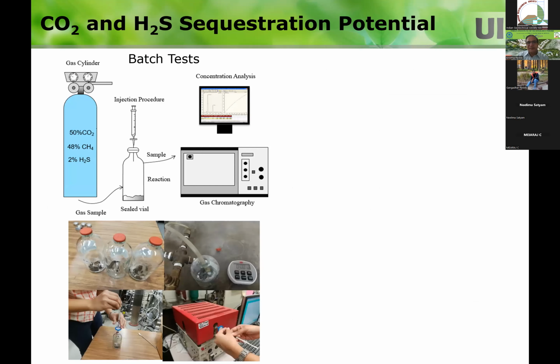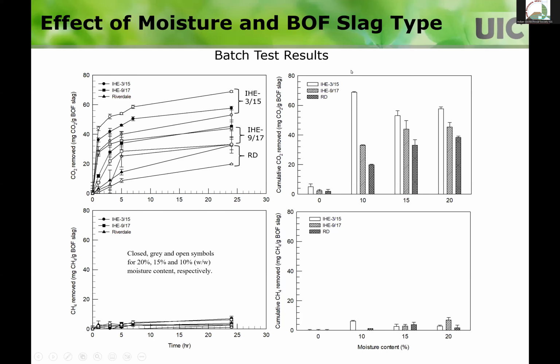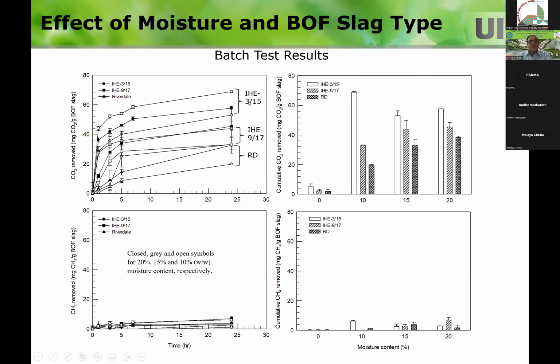Once you know that, the question is, can this slag take out the CO2 and H2S? Can it take out? So what we do is, we have these 3 different slags, and then we did the test at different moisture contents.